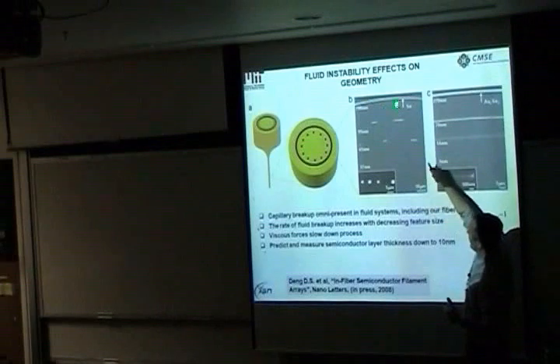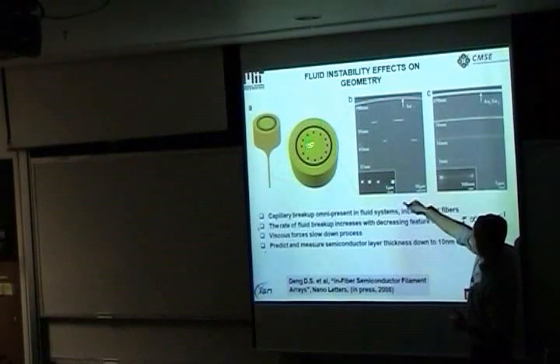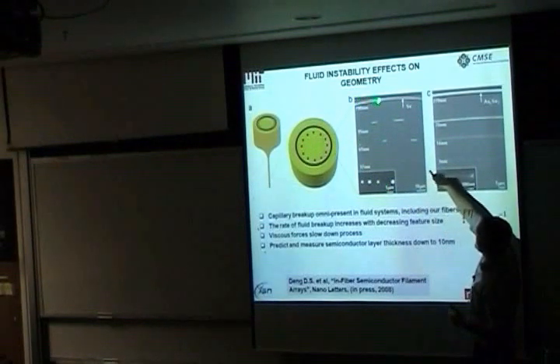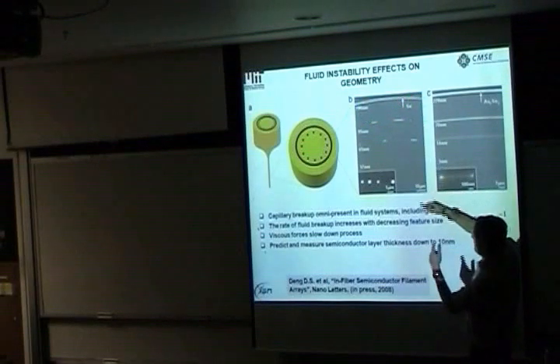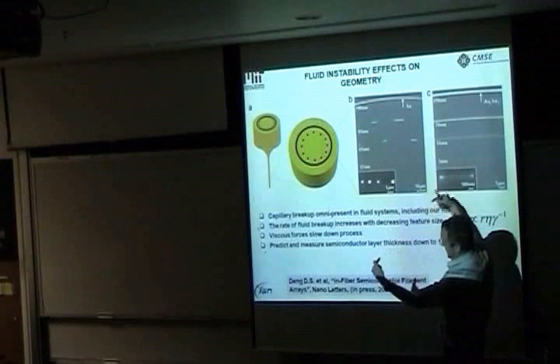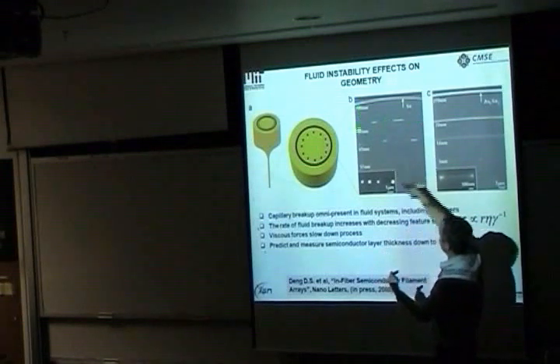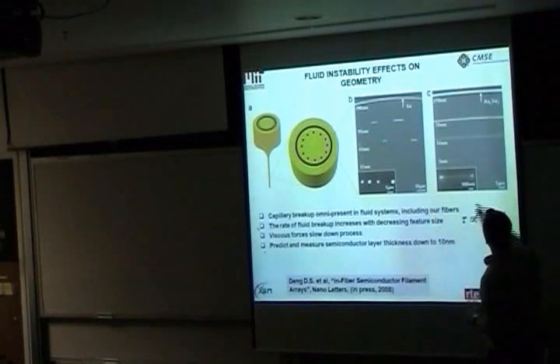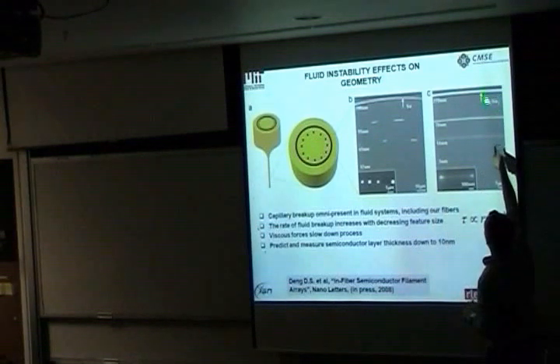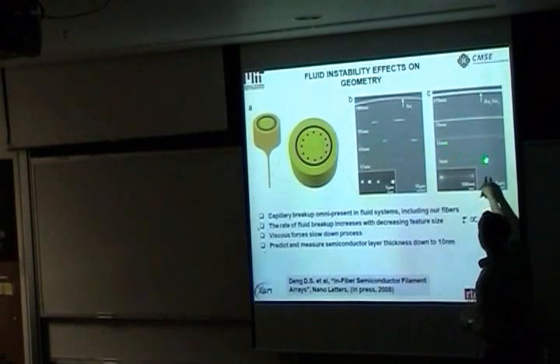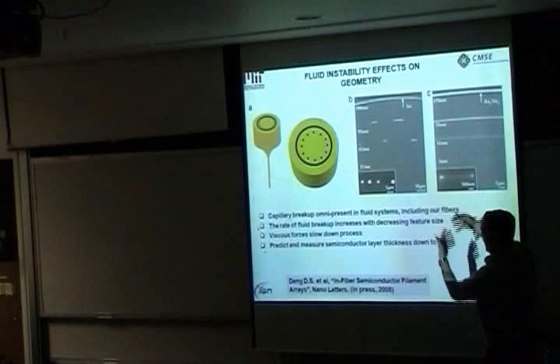So here's an example of a cross-section of a fiber. The semiconductor we're using here is selenium. And you can see in certain cases the selenium maintains its layer thickness. And then as you get deeper and deeper into the fiber, in the radial direction, you see it begins to break up. And here it's breaking up into very small cylinders. On the other hand, if you were to use a different amorphous semiconductor, arsenic triselenide, you find that even going down to very, very thin layers, you maintain it.